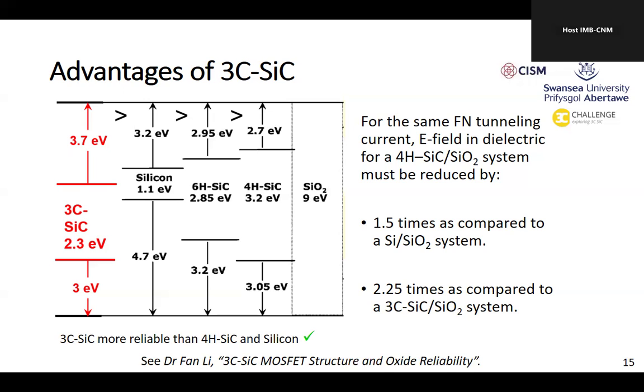And it should be very good for niche applications in harsh environments. This work was also another Horizon EU framework project, which was trying to develop wafer technology for cubic silicon carbide. Traditionally, cubic silicon carbide was grown on silicon epitaxially. So you have a carbonization phase, and then you grow the actual silicon carbide epitaxial layer.